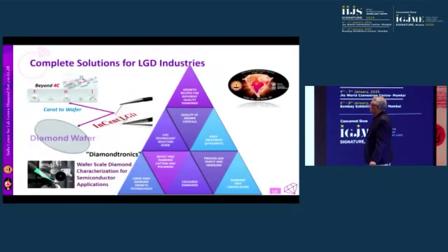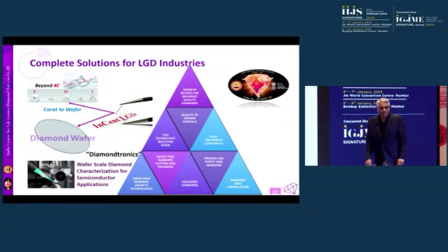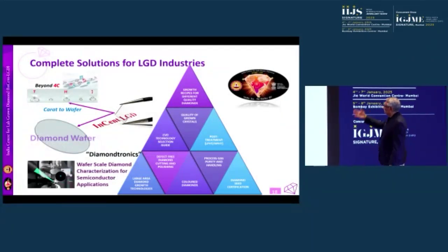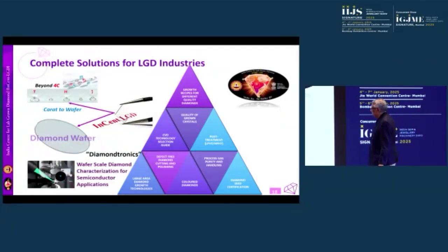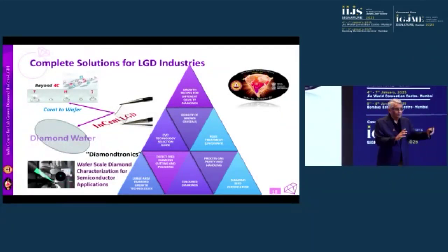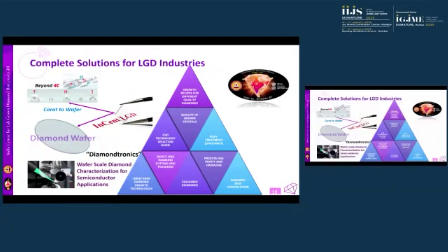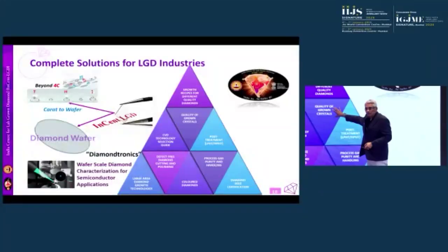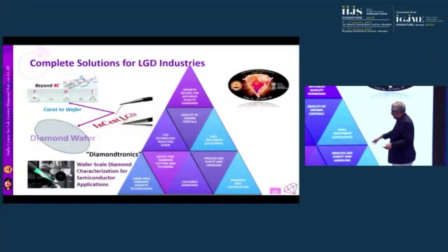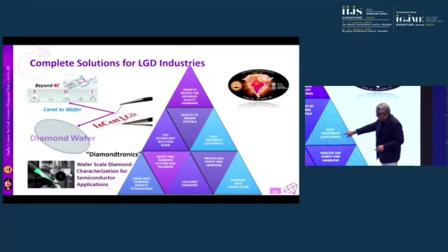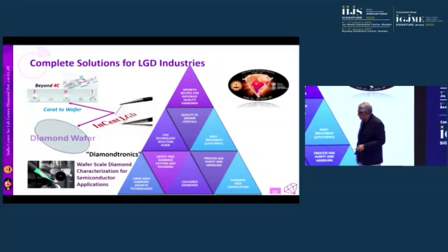Yeah, so the complete solution, if you see, there's not a single point solution. All these things are required. The growth recipe for different qualities of diamonds. There's no single solution for growing gem grade diamond, optical grade diamond, and semiconductor grade diamond. You need to have different growth recipes. And the quality of the grown crystals has to be checked all the time. This is absolutely important. Post treatment has to be done in a judicious way.